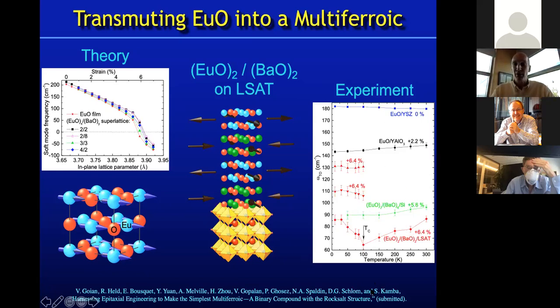Stanislav Kamba has looked at the soft mode in these superlattices compared to the soft mode prediction. So here you can see that a softening is predicted to occur, and where that mode becomes unstable, that indicates going from a stable well to a double well, like a ferroelectric would have. And he can see optically that instability come about at about 100 Kelvin in this hugely strained film. So this is consistent with ferroelectricity, and we also can measure directly on the films the ferromagnetism. So it's a very simple multiferroic made possible by this strain engineering.